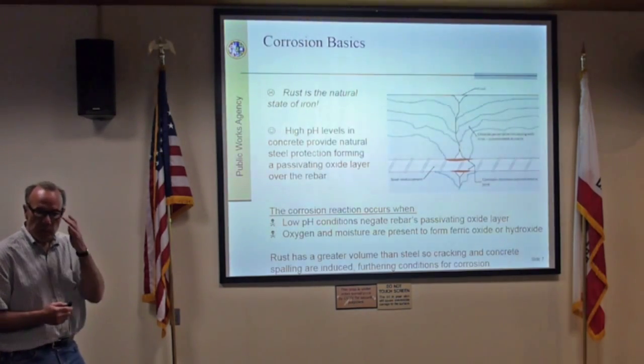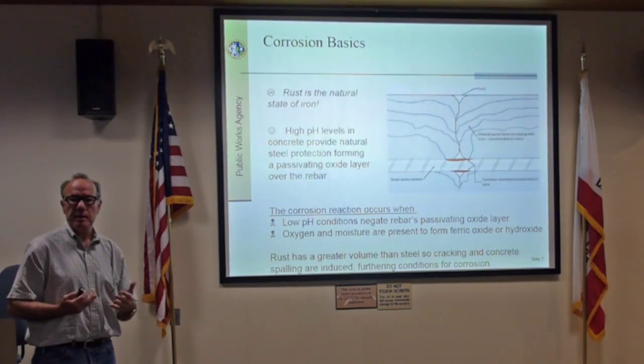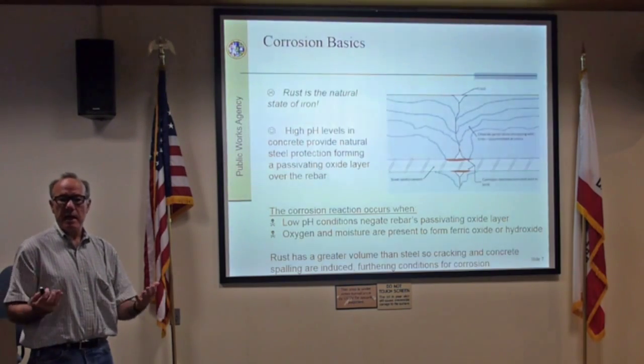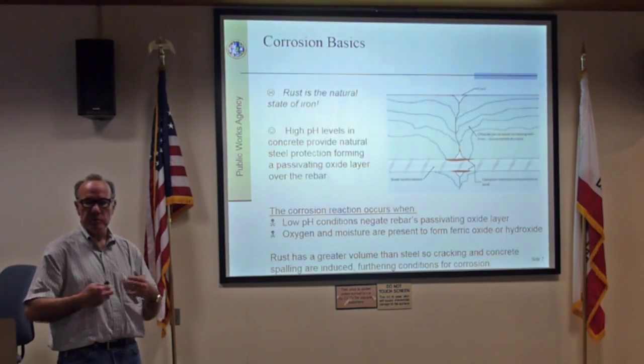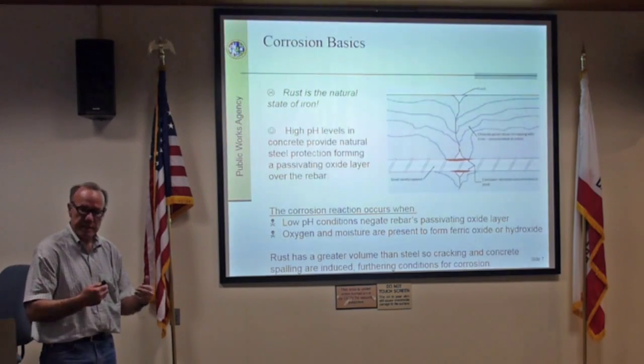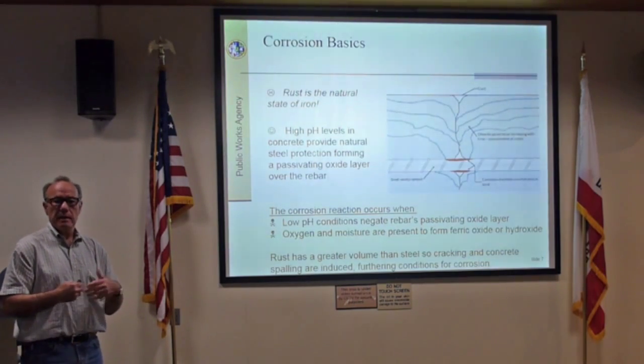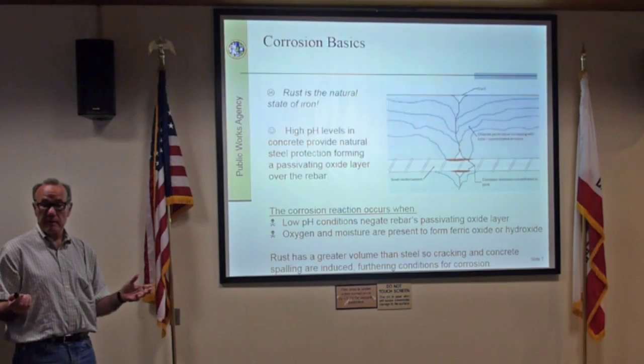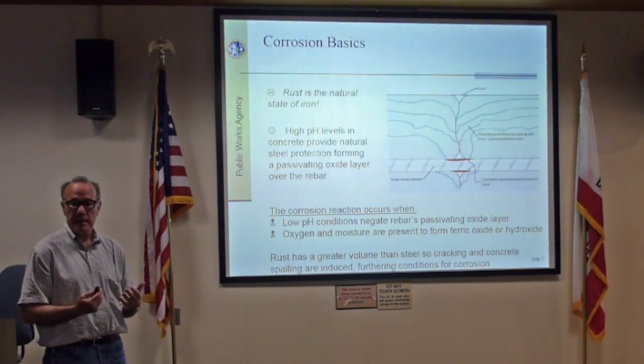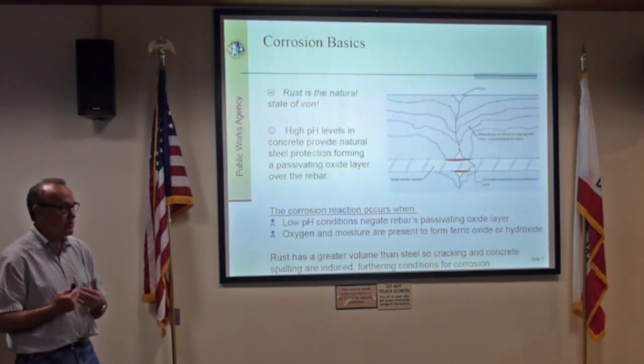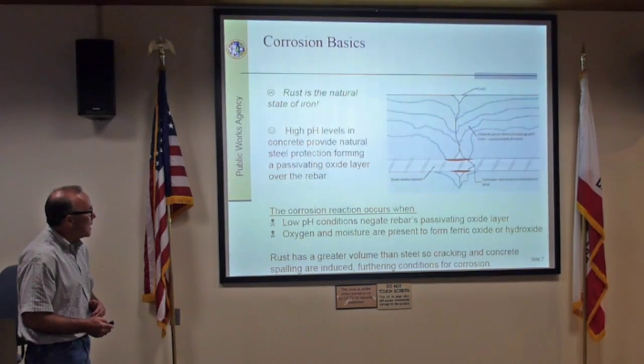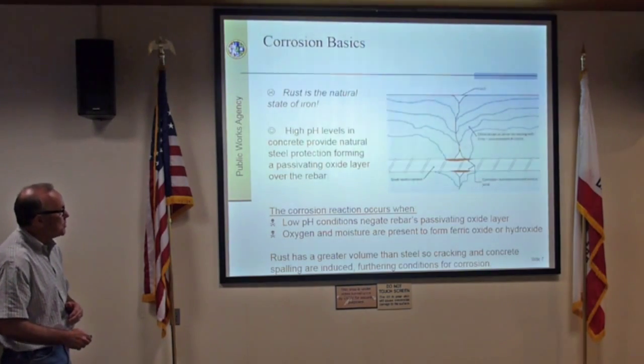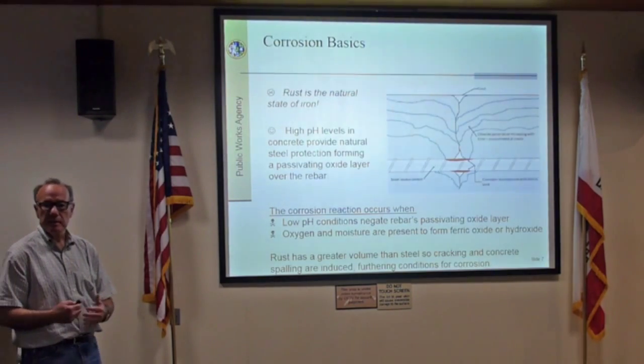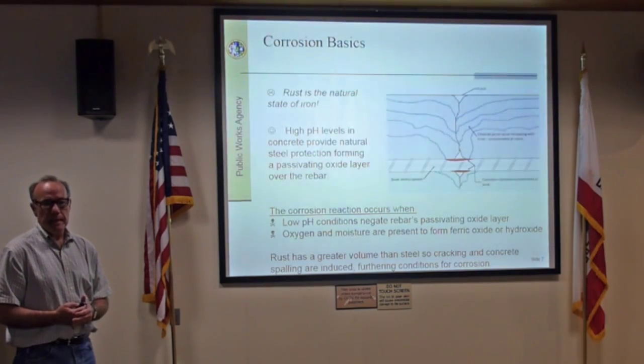And steel, when it's manufactured, just the nature of steel, it wants to go back to its natural state, which is iron. So as soon as you take steel out, reinforcing steel or any kind of structural steel, it immediately starts to corrode. It may be at a very, very slow rate, but nonetheless it wants to corrode. Concrete provides a very high pH environment, so as long as you have a high pH environment in the concrete, it passivates the steel and it's normally very well protected.